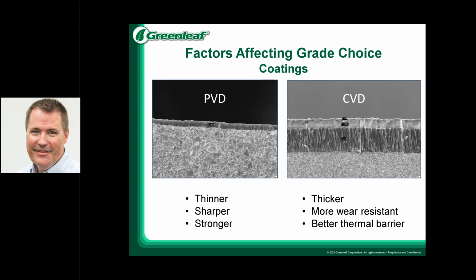On this slide, you can see images of both coatings. PVD tends to be a much thinner coating. The coating itself has higher hot hardness. It's actually typical for PVDs, and I think it was mentioned in the article in Cutting Tool Engineering, that when PVD coatings are run in a process, the heat that's generated helps activate the coating itself, causing it to actually get harder and protect the substrate even better.